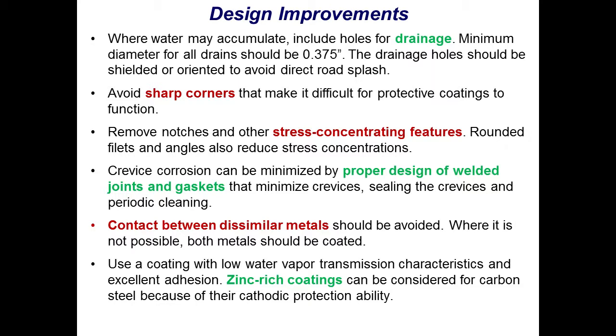So drainage is important. And also, in terms of coating, avoid sharp edges, because like we mentioned, if the coating is dented or somehow has a defect due to the sharp edge or due to the application process, then you have highly localized corrosion going on. It goes much faster. And on top of that, if you have under-deposit corrosion, you could have a highly localized pH drop. It's very acidic. Anyways, it gets really bad to have those designs.